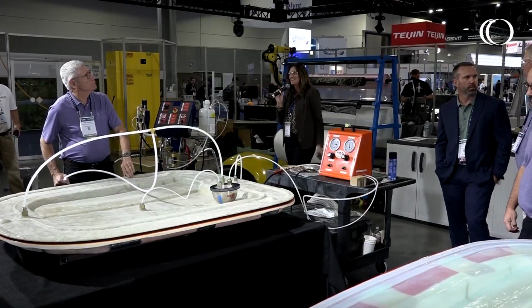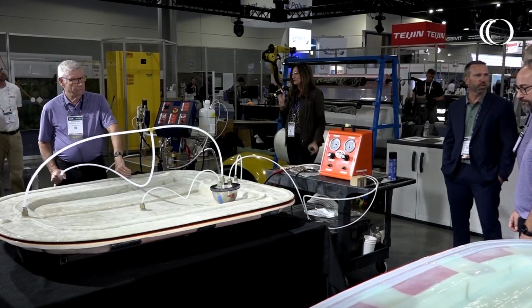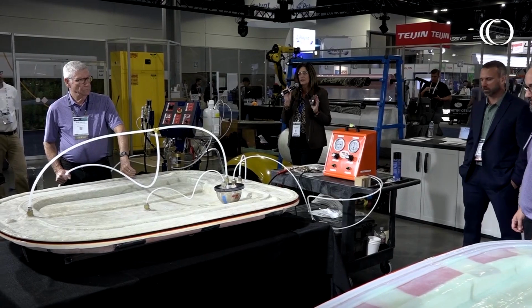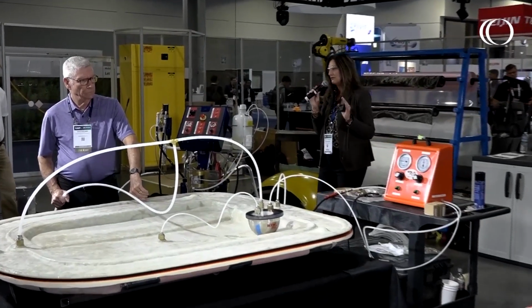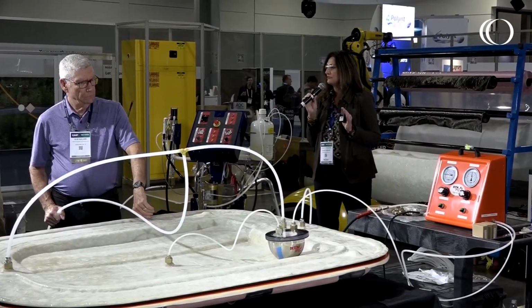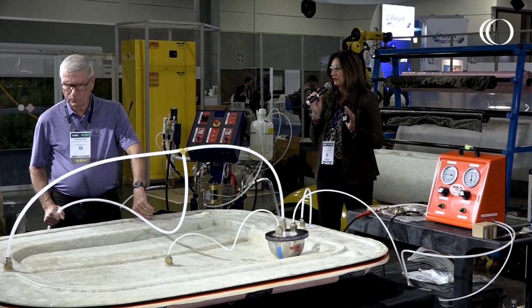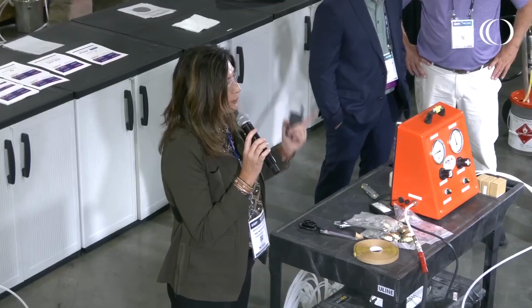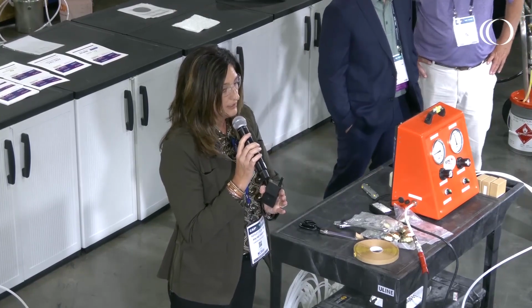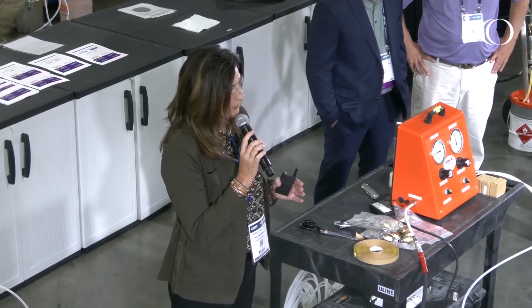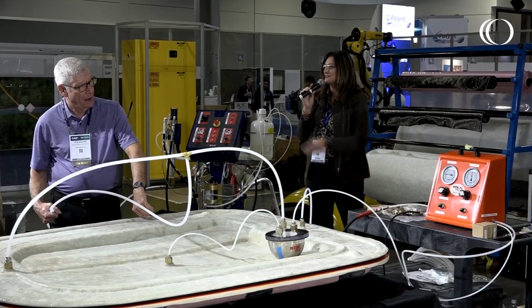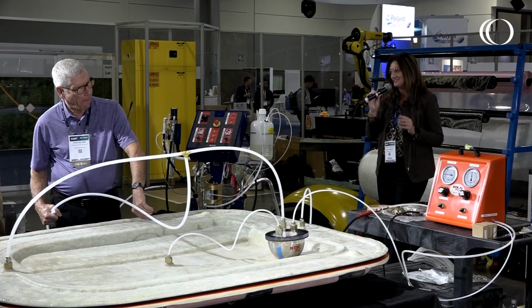There's one more I wanted to show you in terms of the cosmetic comparison. The panel on the left was infused with the 6125, our Polynt A6125 resin, no barrier coat, no skin coat. The panel on the right is a typical infusion resin with no barrier coat and no skin coat. And you can see the surface profile differences in those.